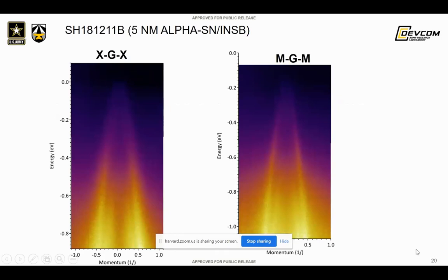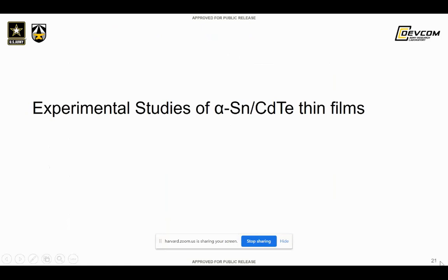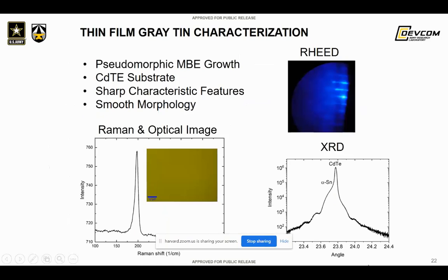And then also look at samples that are on the order of maybe 70 to 80 angstrom, where we expect to see a transition to a Dirac semi-metal in this material. By the time you get to thicknesses that are above, say, about 80 angstroms, it's already a Dirac semi-metal. And we expect to see that transition also in these studies. So that pretty much does most of the data.